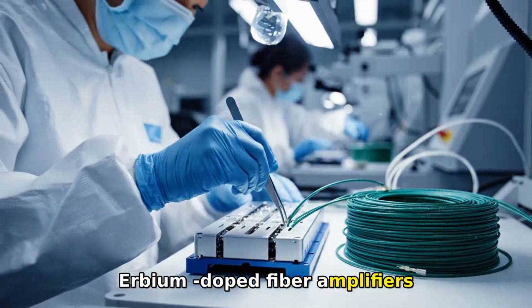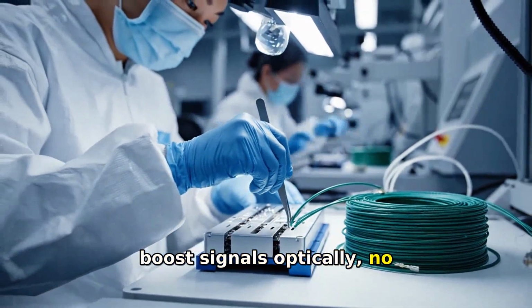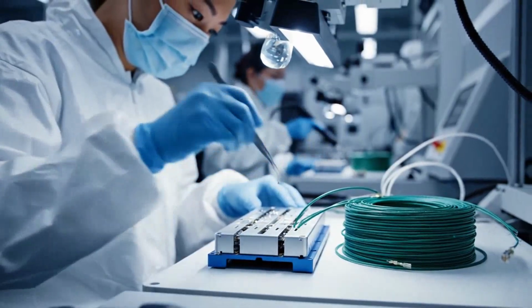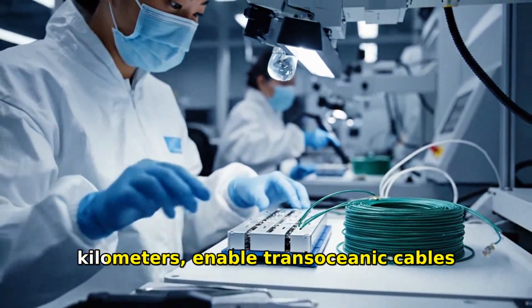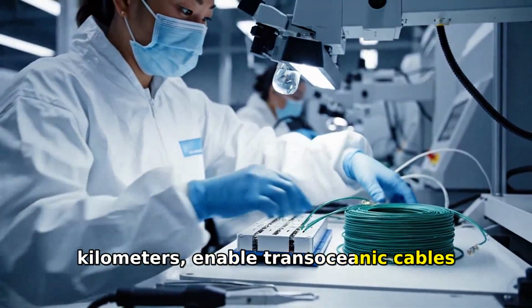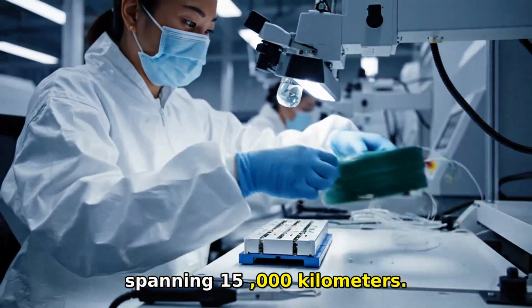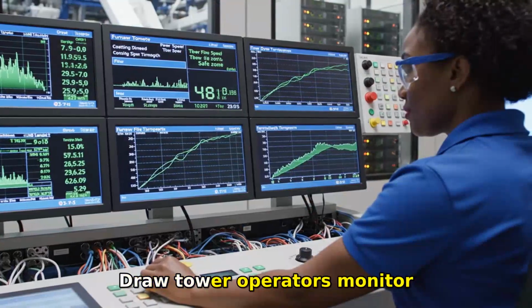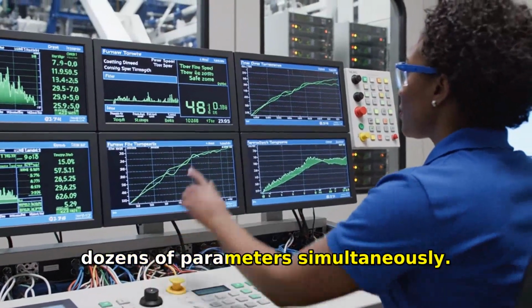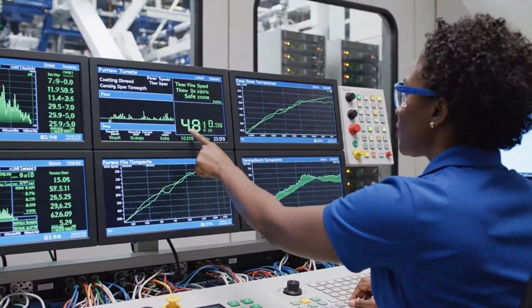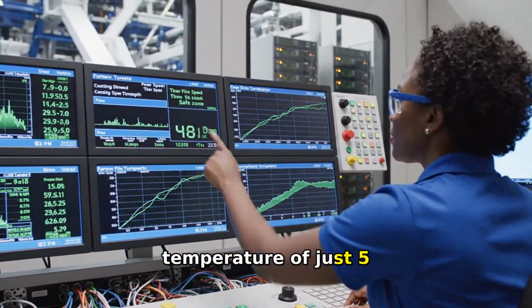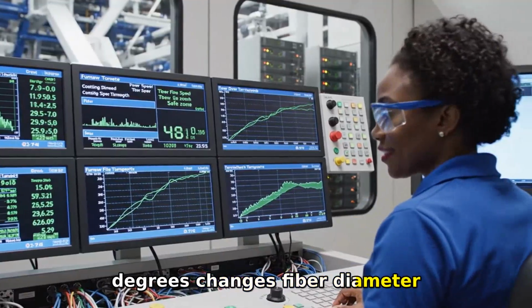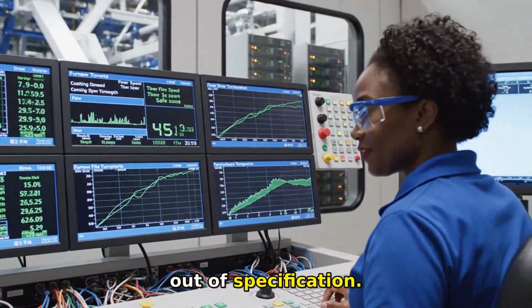Erbium-doped fiber amplifiers boost signals optically, no electrical conversion. Amplifiers spaced every 80 kilometers enable transoceanic cables spanning 15,000 kilometers. Draw tower operators monitor dozens of parameters simultaneously. A deviation in furnace temperature of just 5 degrees changes fiber diameter enough to move it out of specification.